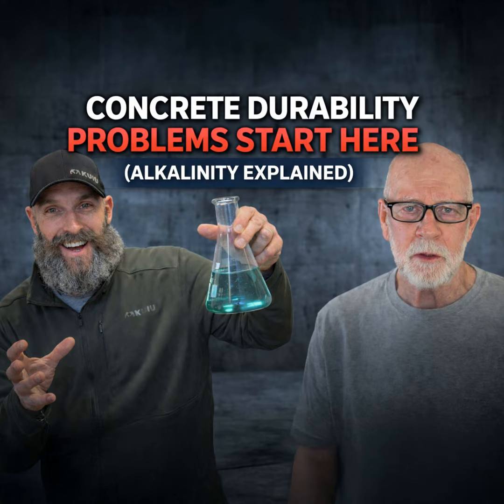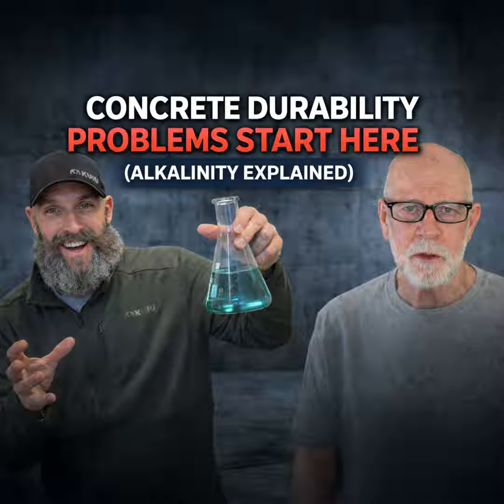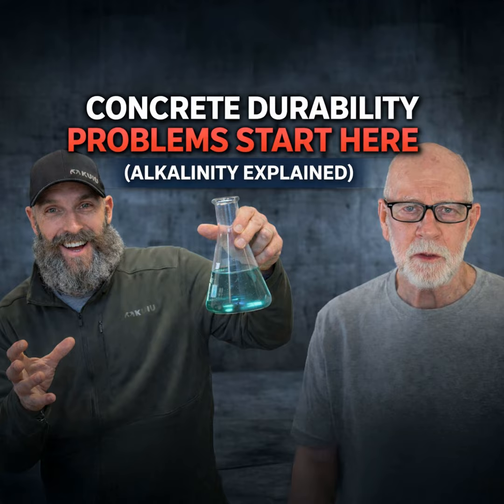What will happen, you'll get a different reading because calcium hydroxide gets more soluble as it gets colder, so it grabs onto the water more readily. But as it warms up, it starts releasing the water because it becomes less soluble. So it starts losing the water. So if you run a calcium chloride test on the same exact concrete, if it's 80 degrees, you're going to get a different reading than if it's 60 degrees. Well, there's no more or less water in there. It's just the ability of that salt under that condition to capture the water.